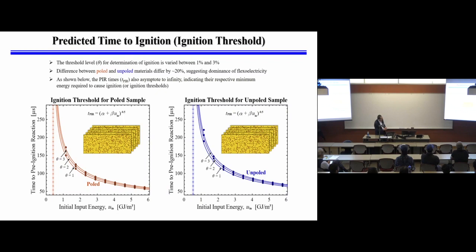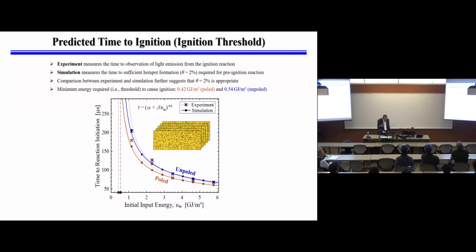So 2% is roughly right. You roughly need about 2% of the particles to be heated enough to get things going, it turns out. You don't need a lot, actually. Once chemical energy begins to be released, then things can happen very quickly. And a comparison between experiments and simulations is actually quite favorable. You can capture the experimental trends very well.